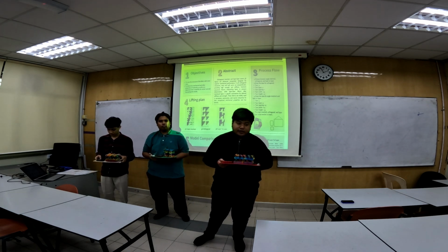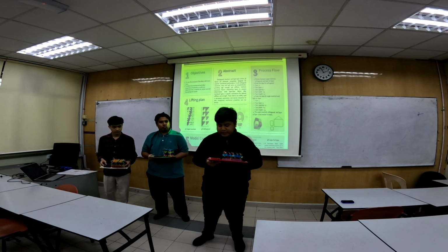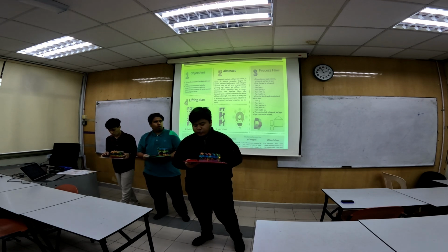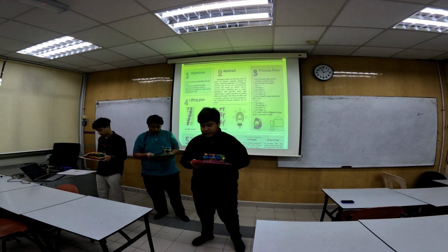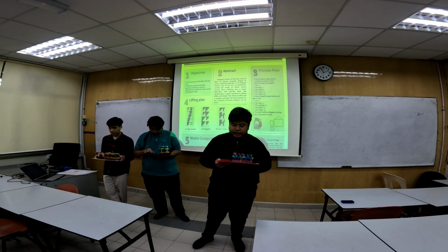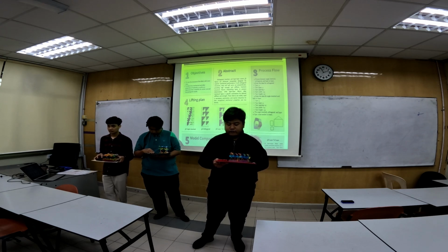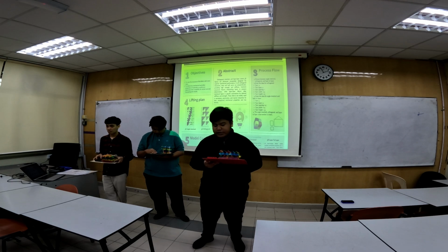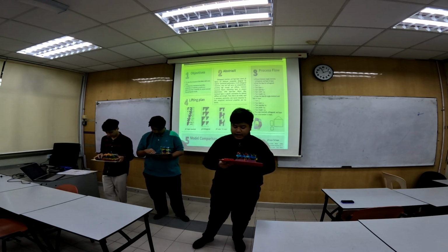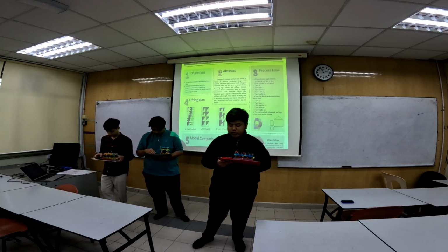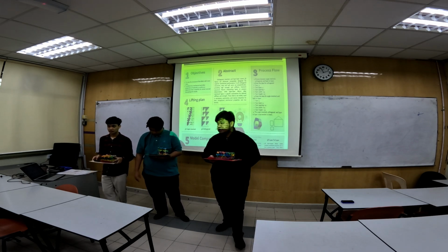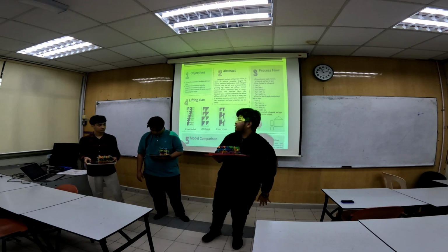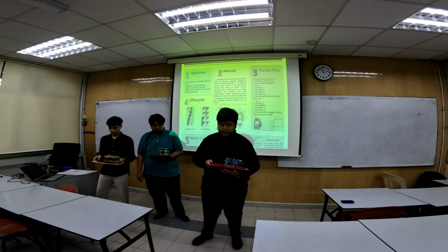In the abstract, you can see that in the orthogonal structure, warp and weft yarns are perpendicular, providing high strength and stiffness. Meanwhile, the interlock structure features interlocking layers to prevent delamination, while layer-to-layer fabrics align interlaced layers in specific orientations for tailored stiffness and stress. In our project, we have 2 objectives.